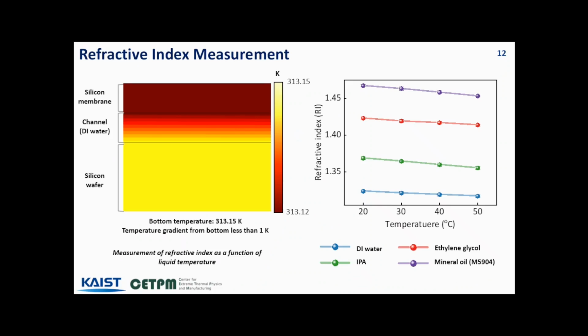The microchannel proposed in this study is made of silicon, making it advantageous for temperature control. According to FEA calculation, when the bottom temperature of the wafer is set, the surface temperature remains within 1 Kelvin. Using a thermoelectric module at the bottom of the wafer, we measure the refractive index of liquids at different temperatures. We conducted measurements on 4 liquids in total and observed that the refractive index decreases as the temperature increases. For 3 liquids with previously reported refractive index data in the near-infrared range, our measurement showed less than 5% difference across the temperature range.